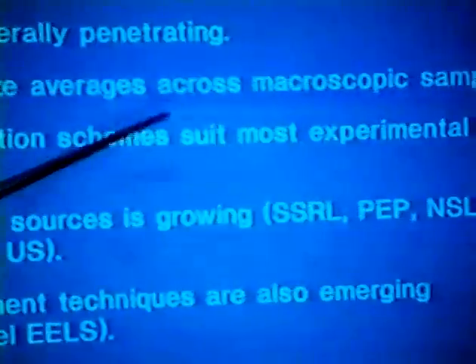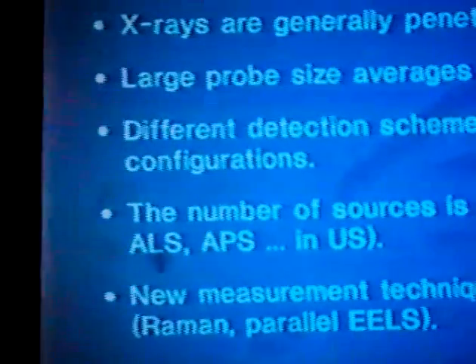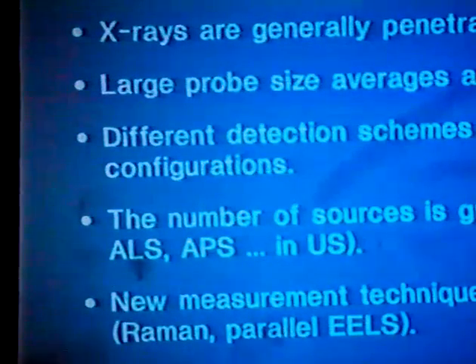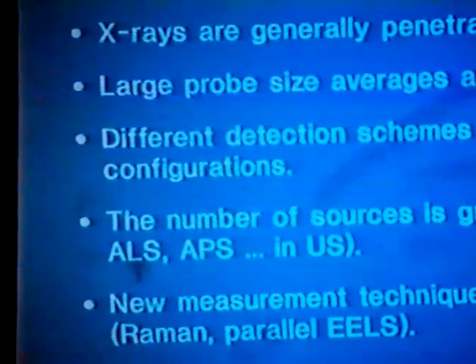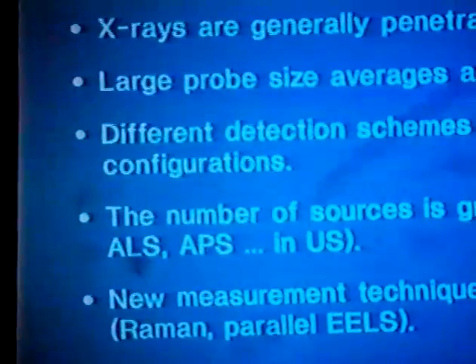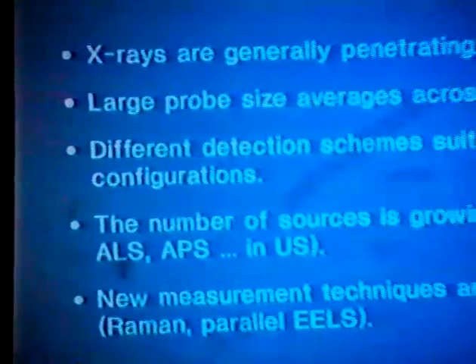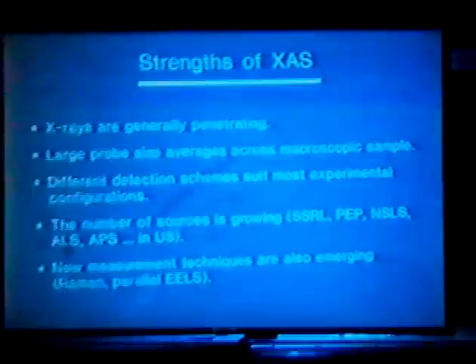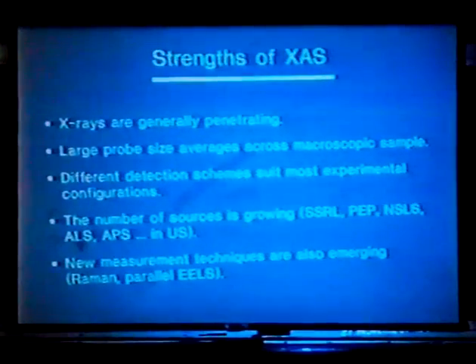EXAFS experiments using a beam from a synchrotron utilize a large-size probe, which averages across a macroscopic sample. That's not to say that you necessarily have a good sample from something that arrived in 90 hopper cars on a train, but the probe size is about 2 centimeters by 2 millimeters, for example. And this is certainly better than, say, an electron microscopist who is measuring on a field that's 10 nanometers in diameter.